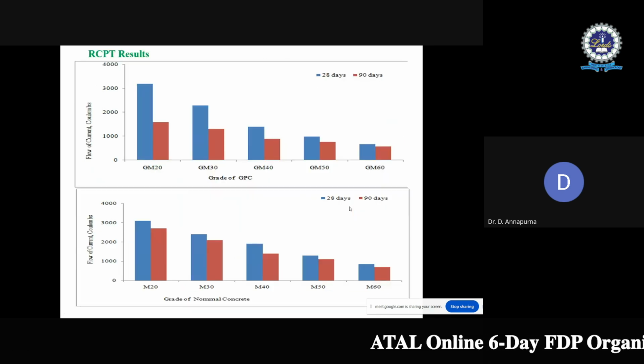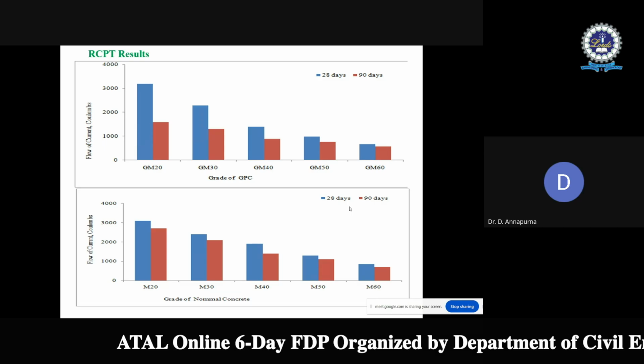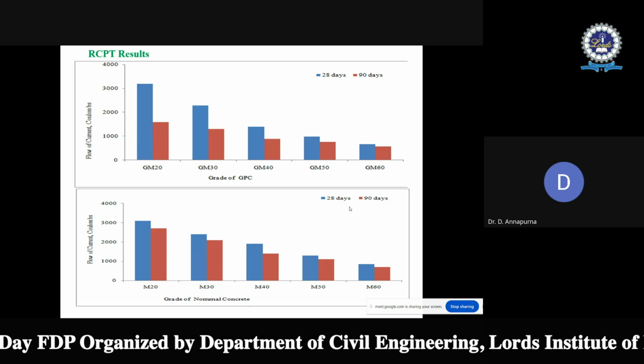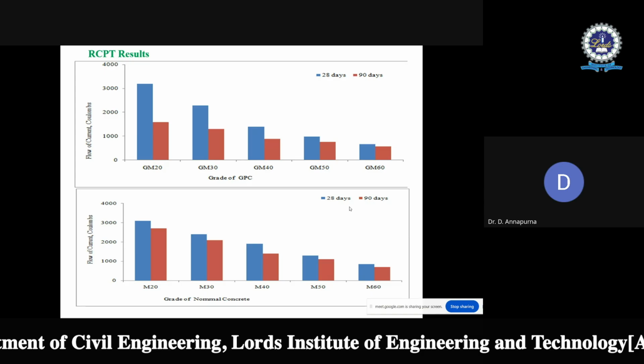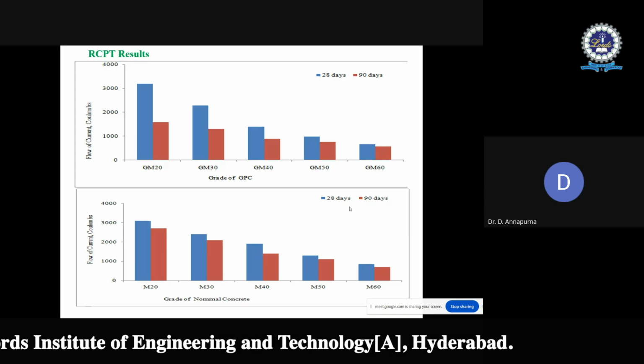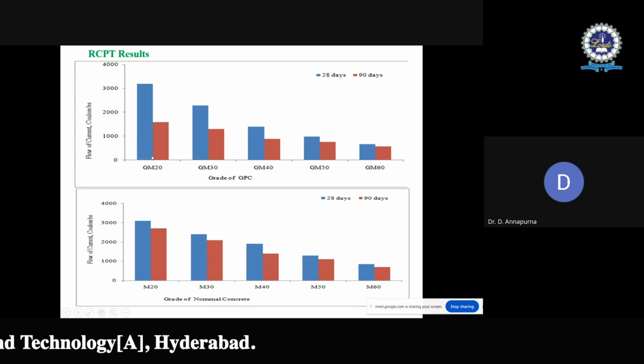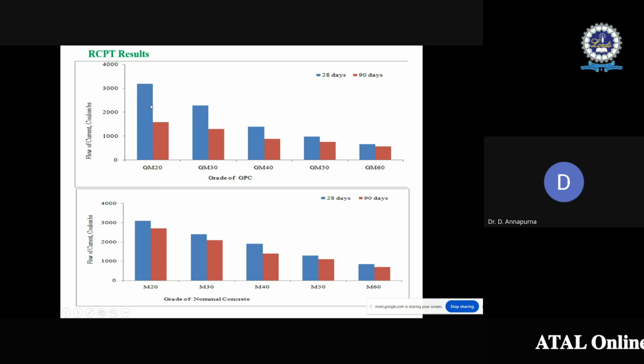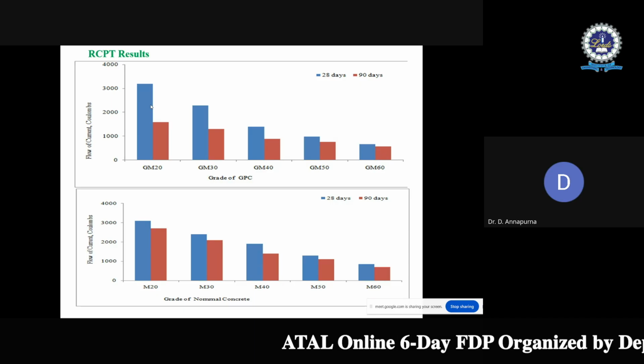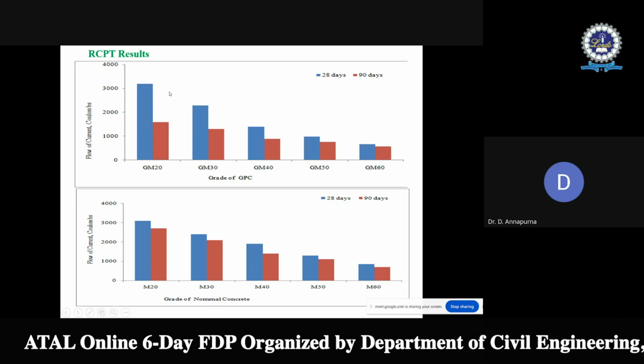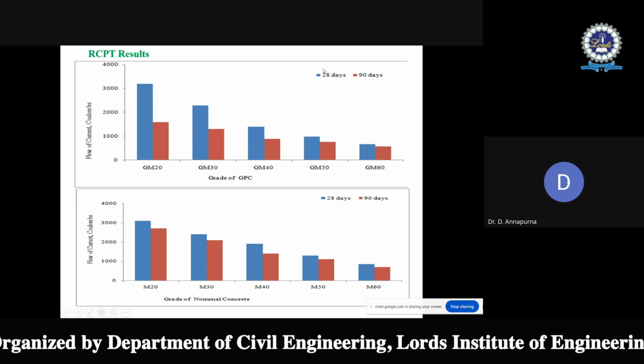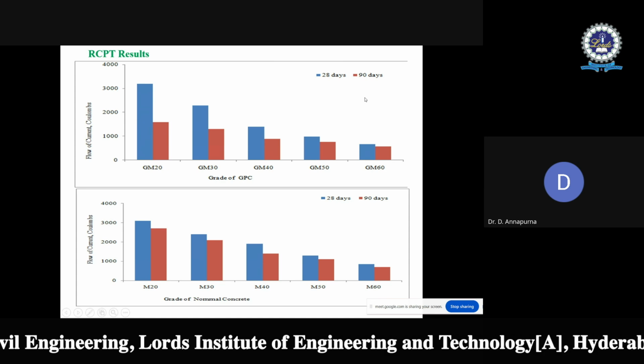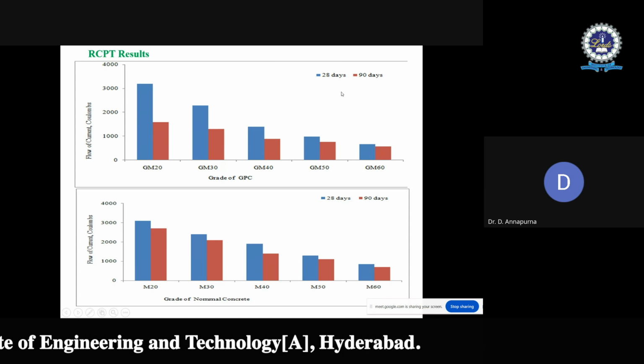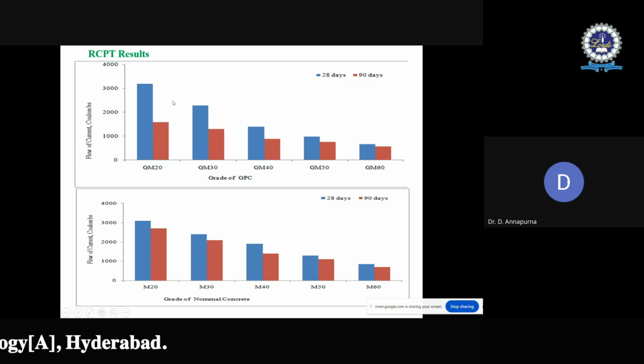After the acid exposure, the RCPT, rapid chloride penetration test, is conducted on the proposed grades of geopolymer concrete. Here, the GM20 sample has only 10% of fly ash. Because of that, its reaction rate will be very slow, and even after 28 days it will not get its full strength. So keeping that in view, both the 28 days samples and 90 days samples are taken out for the RCPT test, and the test is conducted.